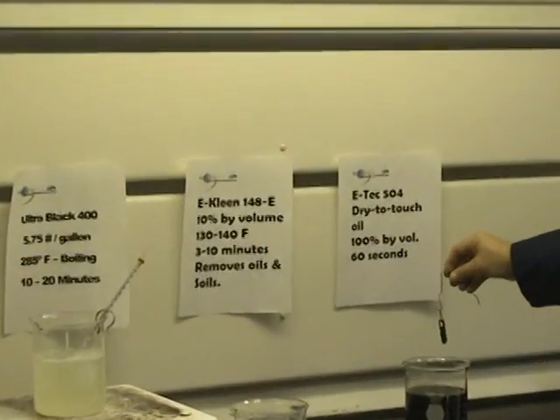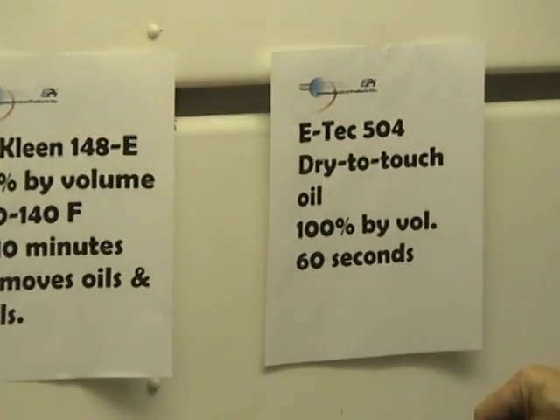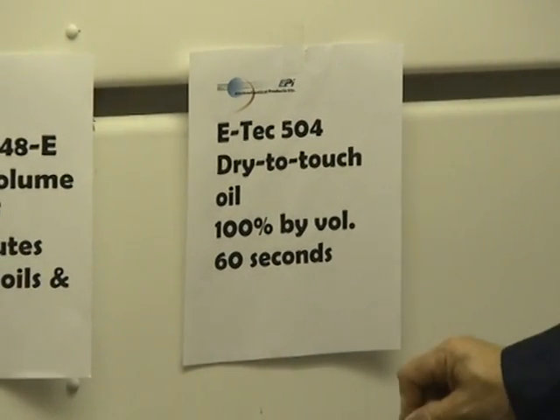Our ETEC 504 is a water-displacing oil that results in a dry-to-touch finish. It'll give you about 48 hours of salt spray.